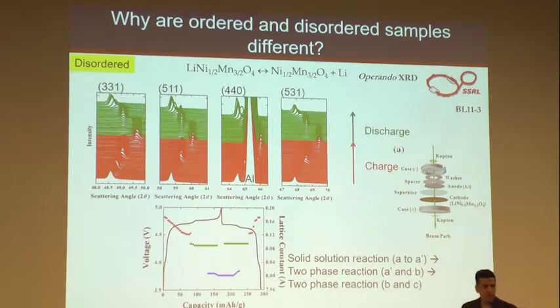So we turn to diffraction. This was done at SSRL, and this is very simple. You take a coin cell like the one that you can buy in the supermarket, you drill a hole through it, you put some sort of window, and you let your X-rays through. Very low-tech experiment. And so we get diffraction on the other side.